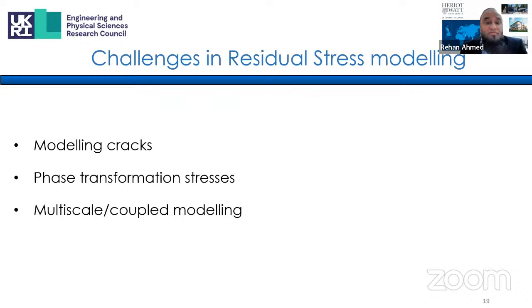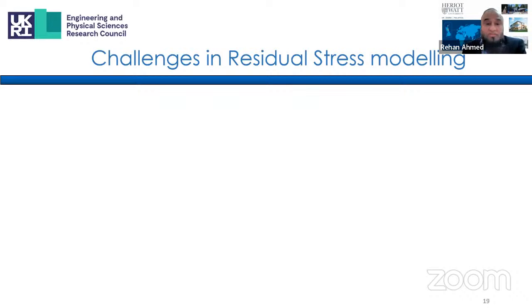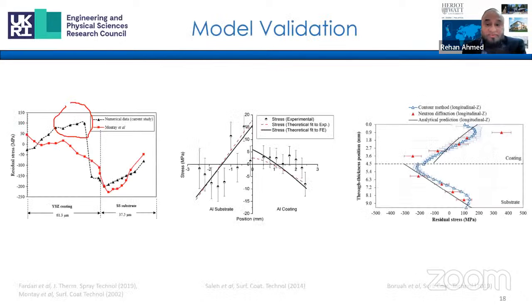And this needs a combination of conventional finite element method with techniques such as extended finite element method to be able to incorporate cracks. There could also be phase transformations during the solidification, or phase transformations related to high strain rate, which are not considered in these models. And these can influence the residual stress to some extent. This may require some form of coupling with molecular dynamics or phase diagram software.